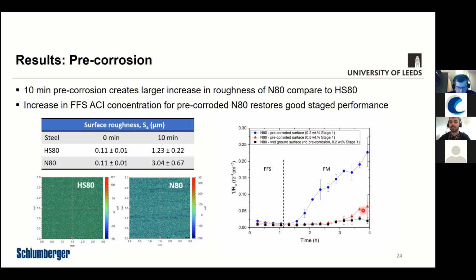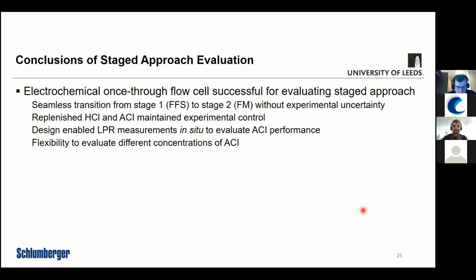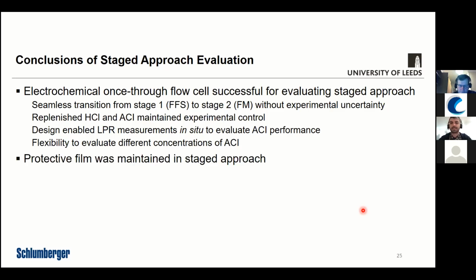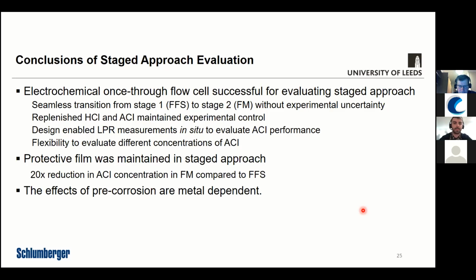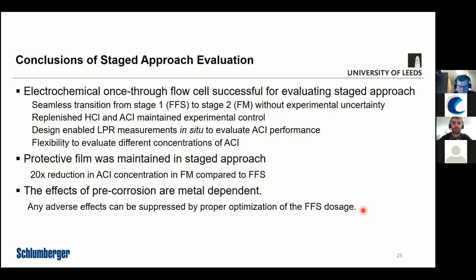So essentially what that told us is that by varying and optimizing the inhibitor doses, we can account for some more variations that we might see in different field conditions. So that's all the results we've got. To conclude, we've shown that the stage approach can be very effective, and the key thing is to establish an effective film during that film forming stage, and then we can maintain that film with a much lower concentration during the second stage. We can see significant inhibitor concentration reductions to maintain a protective film. We do see some effects of pre-corrosion, and optimization of the dosage can influence how significant that can be.